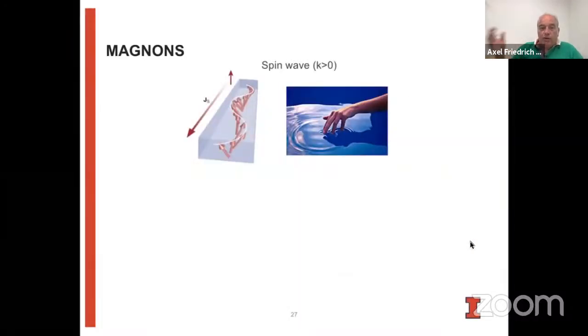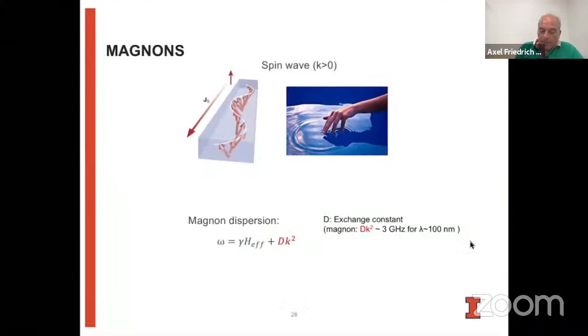Now, this is for uniform modes, but you can also have non-uniform modes where the magnetization in the system precesses differently in different positions of your material. And that then describes spin waves, which is essentially similar to other types of waves, let's say water waves. They are given then by a dispersion. If only the exchange interaction plays a role, it's given by the exchange constant times the wave vector squared. And what is nice is that if you look at excitations at a couple of gigahertz, like the microwave photons that we're interested in, you get relatively short wavelength excitations. They are roughly 100 nanometers. So this makes magnons very interesting because it allows for very compact devices if you want to do things at a microwave frequency.